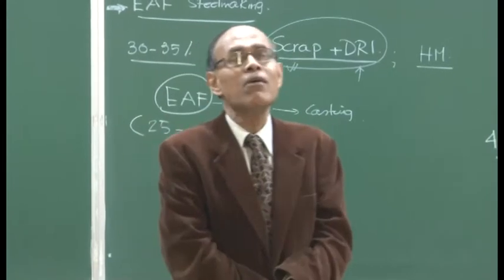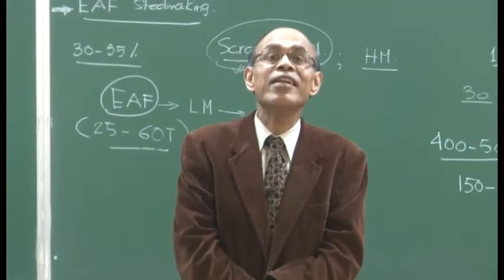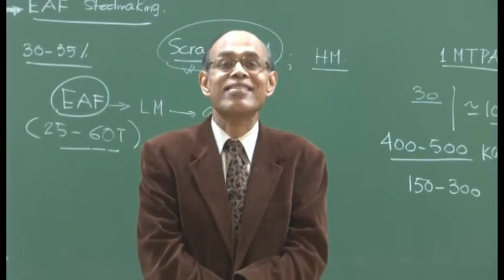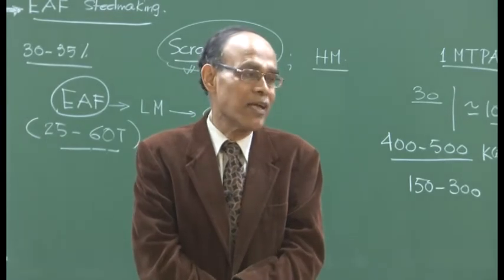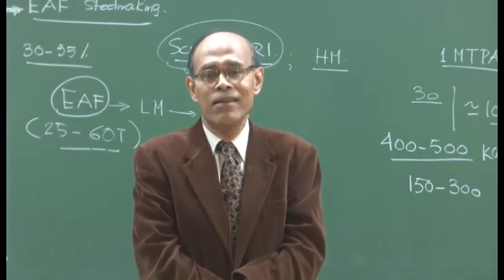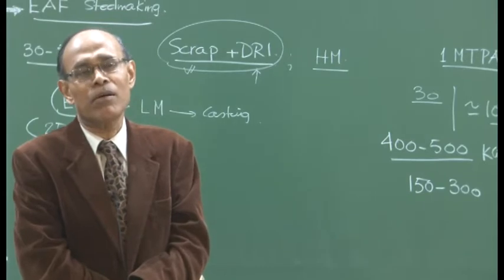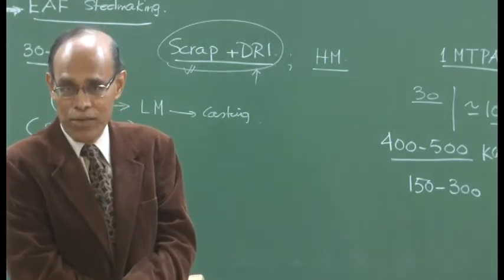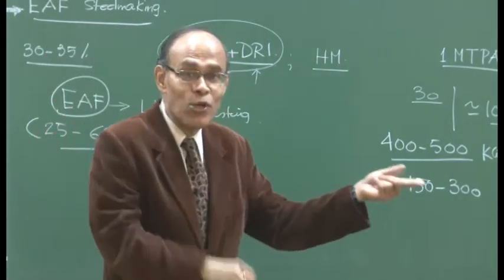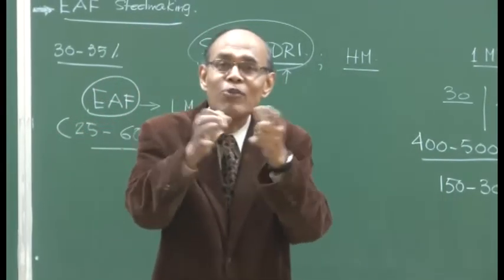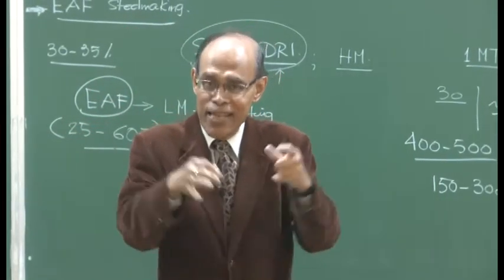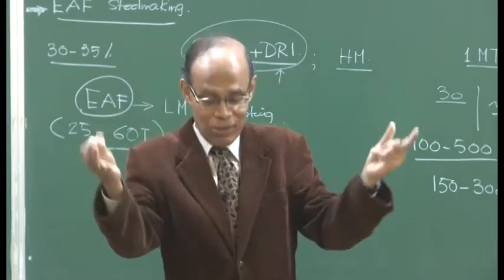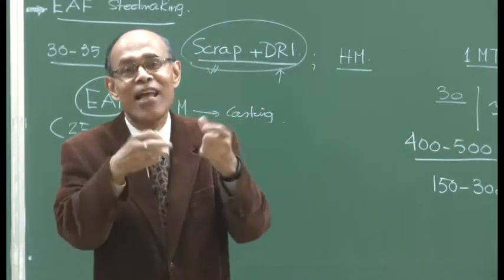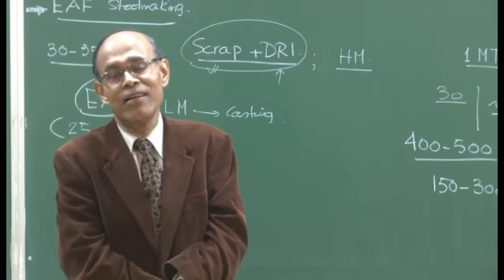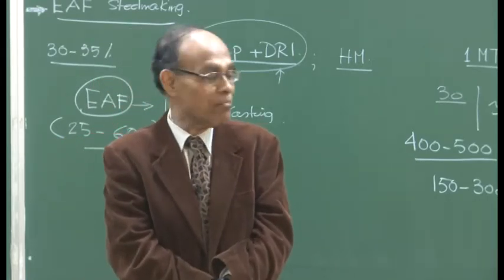So, if you go to foundry industries and you see electric steel making arc furnace, which is used predominantly as a melting unit rather than a refining unit, because the moment we say it is a refining unit, we will try to maneuver the slag basicity, etc., and then if we make the slag basic, then we cannot use an acid lining, because the lining will get eroded or eaten up by the basic constituent of the slag in no time.